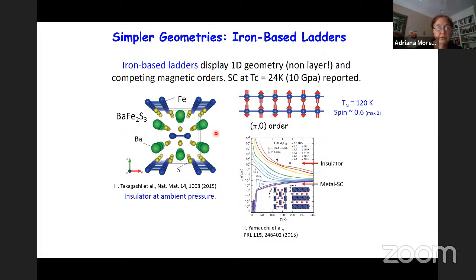In addition, at ambient pressure, the material is magnetically ordered. There is a Neel temperature of 120 Kelvin, and the order that it develops is this structure pi0, antiferro along this direction, ferromagnetic along the rungs.